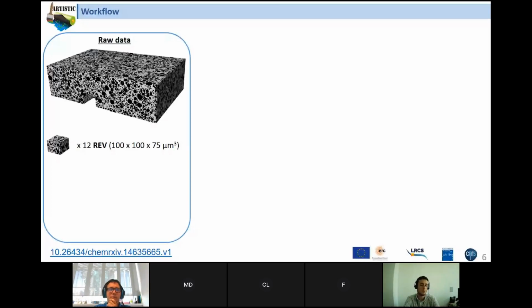And after, what we did was to perform LBM simulations where the electrolyte infiltration dynamics on each of these sub-volumes were simulated using 5 different applied pressures, leaving the rest of the parameters untouched. So in this case, from these simulations, what we obtain is a time series of voxelated data where each of the voxels contains the time evolution of the fluid density. So each of these voxels will contain a time evolution of the density.